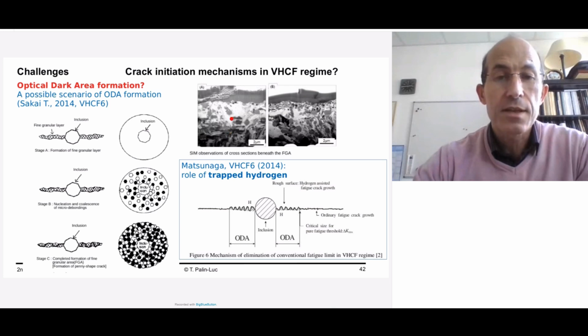This has been observed here by Sakai by cutting a specimen with an inclusion and a fish eye, and he observed by transmission electron microscopy that in some locations around the inclusion, he can observe very small grains, nanograins, which do not exist elsewhere in the material. So he said that this recrystallization in nanograins is due to the cyclic loading and microplasticity accumulation around the inclusions.